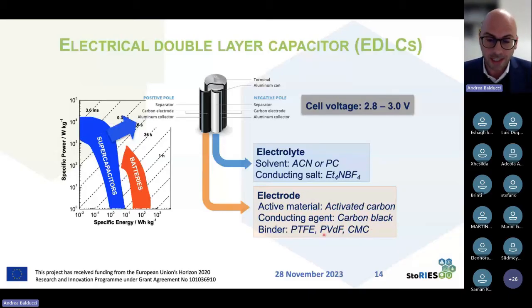So the conductive agent and the binder are basically analogous to the ones that we are using in many lithium-ion batteries. The active material is then a carbon, but not a graphite, but an activated carbon, which is a porous carbon, which we will discuss later on. As electrolyte, what is used are solutions of organic solvent, typically acetonitrile. Propylene carbonate was used in Japan because acetonitrile was banned in this country for many years, but right now most of the systems are working with acetonitrile.